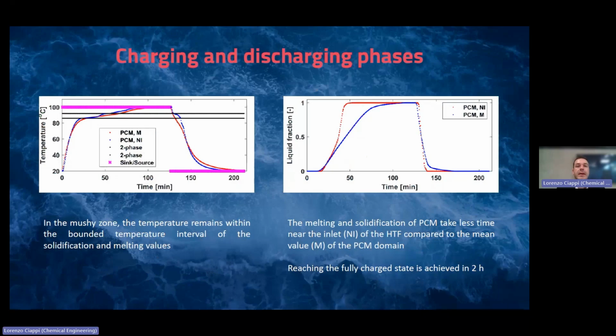Here we can see the processes of charging and discharging of the system. The charging phase starts with the thermal equilibrium between the phase change material and the reference temperature at 20 degrees Celsius. Starting with the charging phase, the heat transfer fluid starts to release sensible heat to the phase change material, which increases its temperature, undergoes the melting phase, and then again increases its temperature until reaching the equilibrium with the temperature of the source.